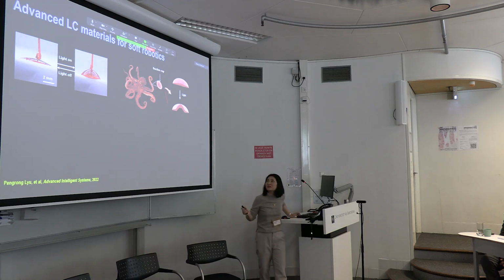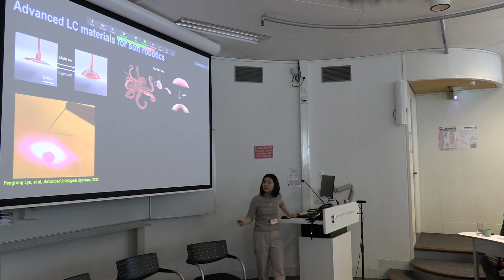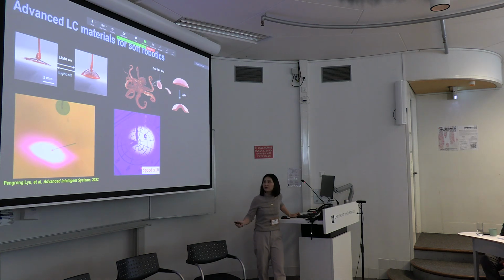And we say, okay, this is like an octopus suction cup, and the octopus suckers use vacuum to pick up things. So what we do is mimic this, and we make a film, and you can see that we can pick up a glass plate that is hundreds of times heavier than this polymer. This time we use light to trigger the response, and then we can further even connect it to an entire robotic arm.